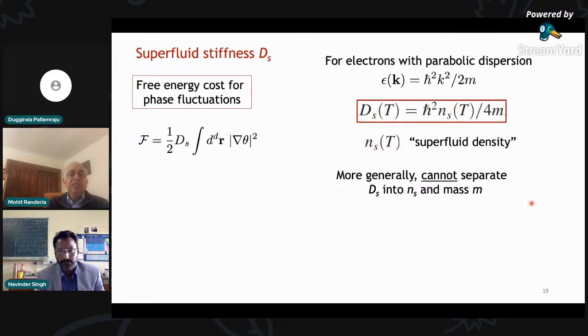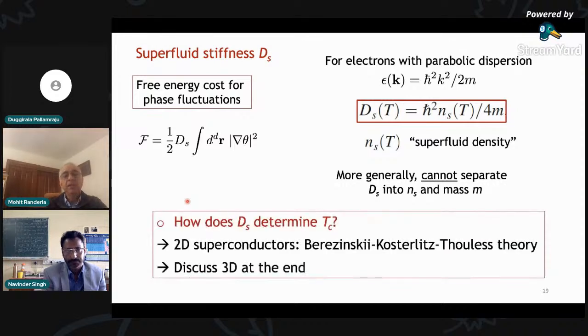But more generally, the reason for not talking about superfluid density, but rather the stiffness itself, is that if one doesn't have a parabolic dispersion, one cannot separate the numerator from the denominator and say there is a numerator which is a superfluid density and a denominator which is a mass. It is only this combination, ns over m effective, which enters Ds, and therefore controls all the experiments and the phase stiffness that I talked about. That's why I'm talking about the superfluid stiffness rather than the superfluid density.